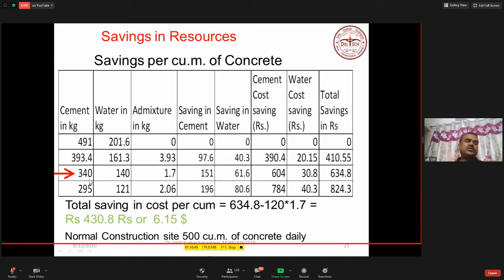Similarly, if I use, suppose, admixtures, mainly we are using here the PC-based admixtures that can reduce the water by 40%. So if we can reduce the water by 40%, then what happened? It is 201.6 minus 40% of 201.6. So I will get 121 kg water, and water cement ratio is 0.41. So I will get cement equals to 295 kg.